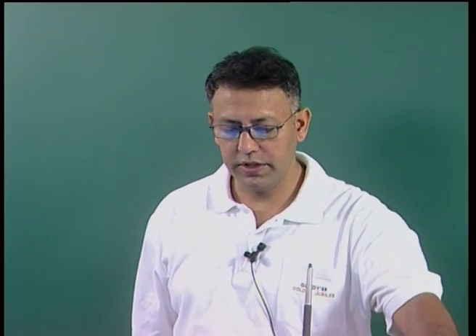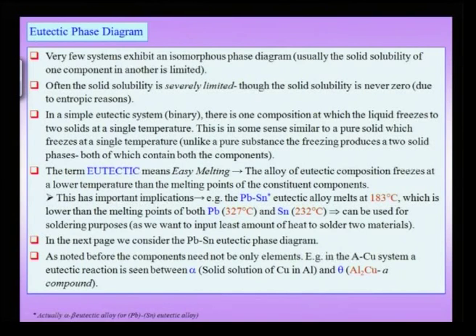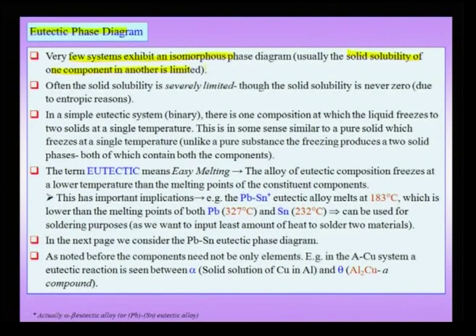Next we consider a special kind of phase diagram — the eutectic phase diagram. In the eutectic phase diagram there is something known as a eutectic reaction. Very few systems actually exhibit the isomorphous phase diagram, and usually the solid solubility of one component in another is limited — we are not in the regime of Hume-Rothery rules. We typically see other kinds of phase diagrams in which solid solubility could be severely limited. Truly speaking, the solid solubility is never 0; due to entropic reasons, there will always be some small amount of solubility.